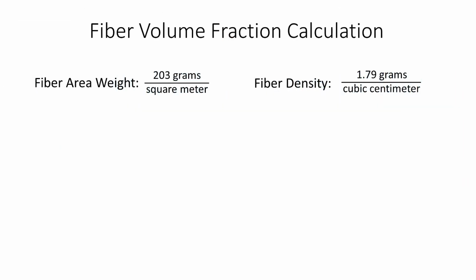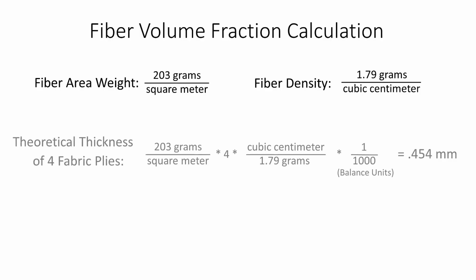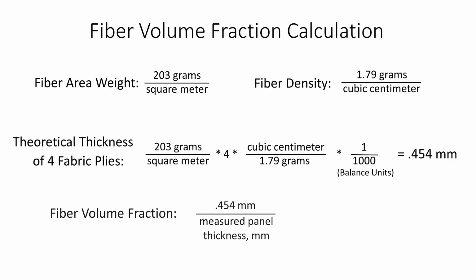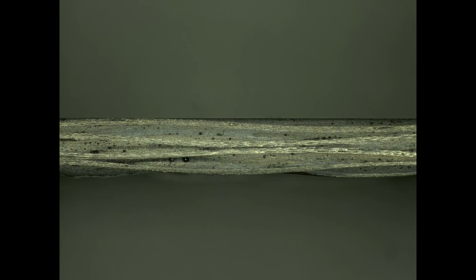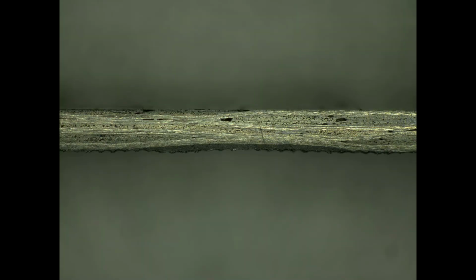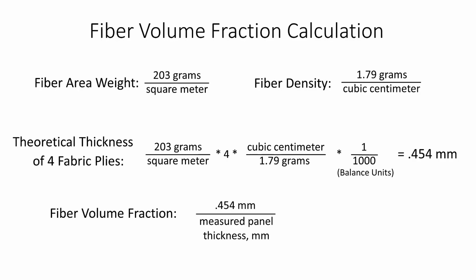For all samples, fiber volume fraction was calculated. The fiber weight fraction was calculated based on the weight of the fibers and the weight of the final part, and then this was converted to a fiber volume fraction estimate with the densities of the fiber and resin. Porosity and void content must be determined, which could be done with microscopy and image processing software, but was not due to the large number of samples and the preparation required to produce an accurate result. Instead, the thickness was measured and the volume fraction is calculated based on the area, weight, and density of the fabric as well as the fiber weight fraction.